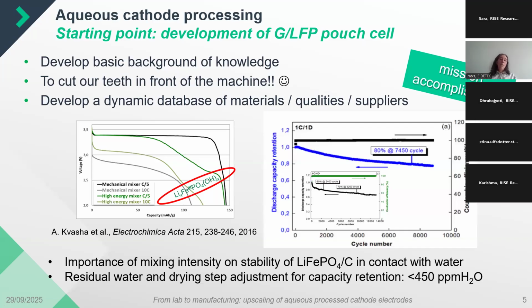If this residual water is too high, then this water can be released within the cell during operation and react with electrolyte, generating HF, and of course a reduction in the performance of the battery that has been manufactured with this kind of electrode.